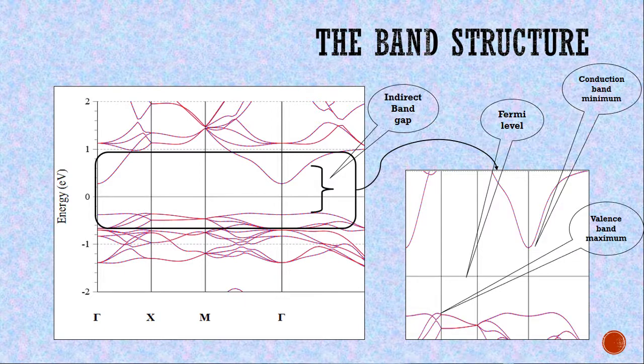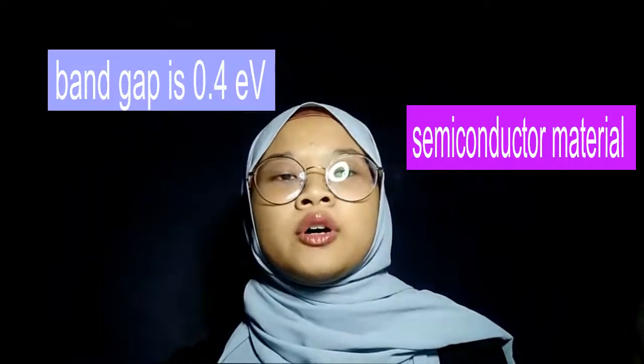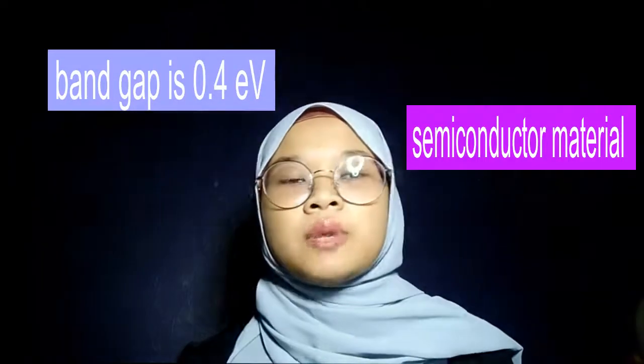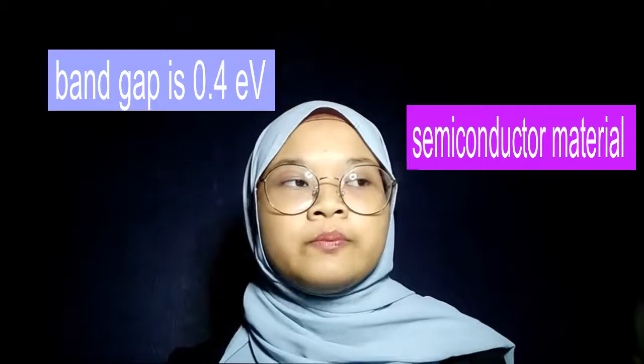Okay, now it's shown the graph of band structure. Based on the graph, the band gap is said as the indirect band gap between the lower part called the valence band maximum and the upper part called conduction band minimum near the gamma symmetry. The band gap is at about 0.4 electron volt that we can suggest this pyrite is semiconductor material.